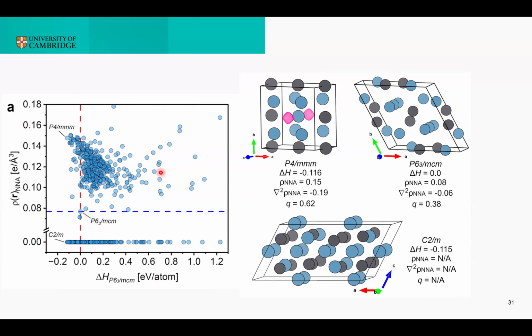So in this case, all this block or area where you see that there are phases with a value that is non-zero for the non-nuclear attractor, all of these are potential electrides. Well, here this line at 0, those are all phases that are not electrides because a non-nuclear attractor was not found. Now my search found another phase that is this P4/mmm, that is up here. And that would be both the most stable and also quite a real electride.